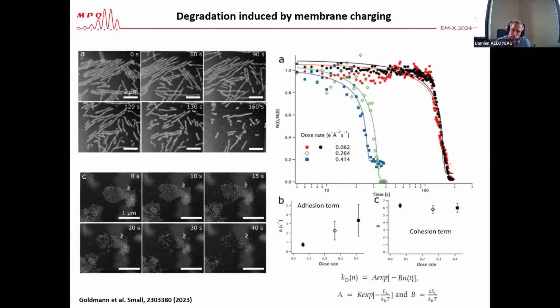nanoparticles. And what is interesting with these models is that you have in this A term here, it depends on the adsorption energy, so all the force that sticks the nanoparticles on the membrane, and a term that depends on the cohesion energy, that is all the force that holds together the supercrystals. And you see that when you change the dose rate, the cohesion term is not varying, whereas the adhesion term is drastically changing, meaning that, so these results indicate that we are not degrading the supercrystal, we are changing the affinity of the nanoparticles for the membrane.